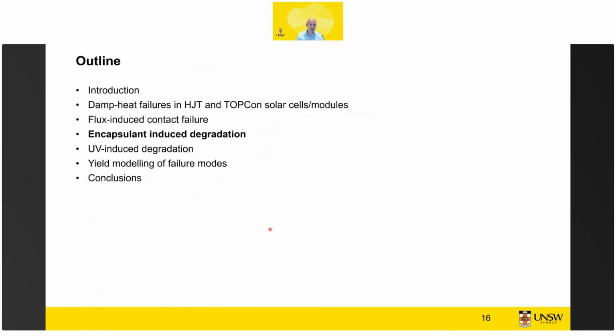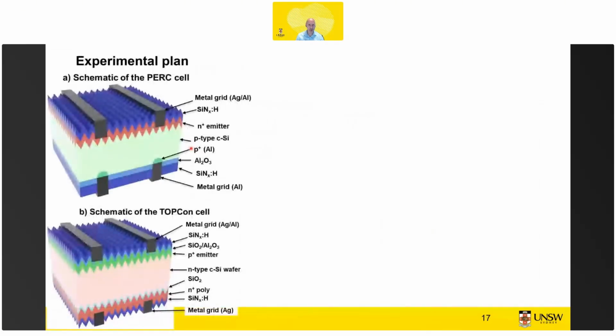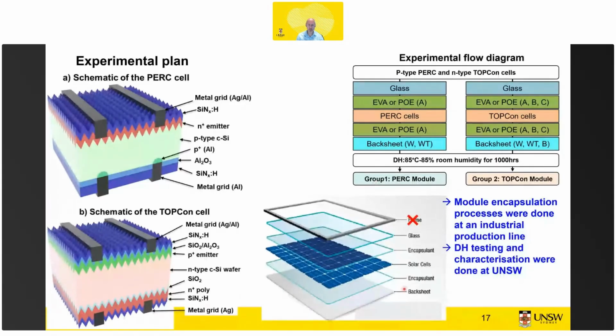So the second part is encapsulant-induced degradation, and this is work that we also showed previously. But now we can show you a lot more on the root cause, because we've made a lot of progress there, where we tested various EVA and 3 types of POE for the TOPCon in glass-backsheet modules. So this is module level testing. But of course, most TOPCon modules are glass, and they are glass in part because of this failure mode.